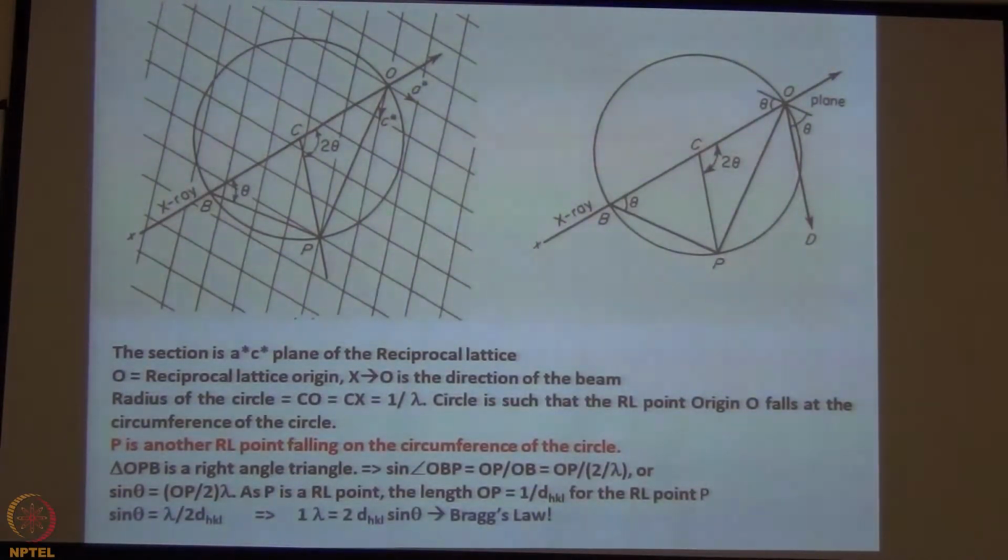So all the points which are there in this diagram, all the points of intersection by rotation of the crystal, can be made to pass through the circumference of the sphere that we are constructing, assuming the wavelength is lambda.